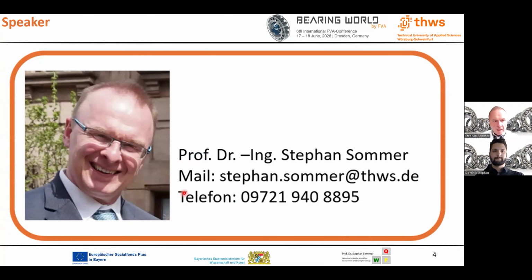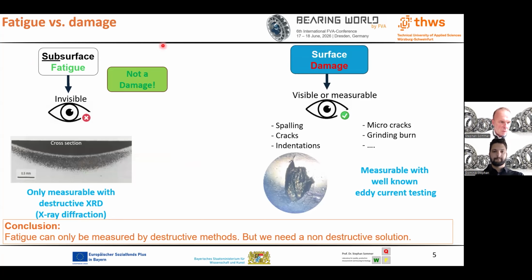Now this is me, and I start the first part. Fatigue versus damage. So what is fatigue? Fatigue is not a damage, and fatigue is not visible from the outside. So here is a cross section, and this here is the surface. And we see under the surface this half moon shape. This is the dark etching region, and this is the fatigue that you can see under the surface, but only after you cut the ring. This is only measurable with destructive X-ray diffraction.